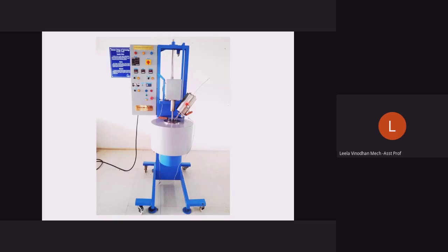For example, taking boron carbide, we will preheat at 200 degrees Celsius. If you have some other carbon material, then we can go higher, 300 or 400 degrees Celsius also. We are supposed to take the moisture out, and moreover, certain reinforcements are required to be preheated to a particular temperature so that they mix with the aluminum properly. Once we put the reinforcement in this chamber, otherwise called a mini furnace, we can maintain it for 10 minutes or 15 minutes, keeping this furnace at 300 degrees Celsius or a maximum of 400 degrees Celsius.